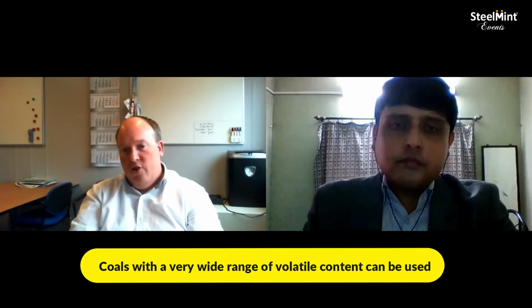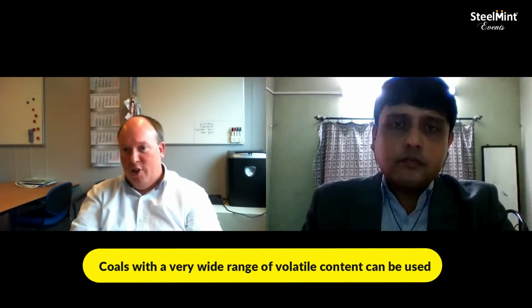Right. And so the kind of the grade of coal that producers should look at, coal of what kind of a calorific value? If you could just give us a. Not from the top of my head, don't know the calorific value, but we've used coals with a very wide range of volatile content, and we've basically tried anything from less than 10% volatiles to nearly 40% volatiles. It all works, but if you get to 40% volatiles, you make so much gas that the plant is difficult, if not nearly impossible to operate. But we normally run anywhere between 10 and 20% volatile content, for example.